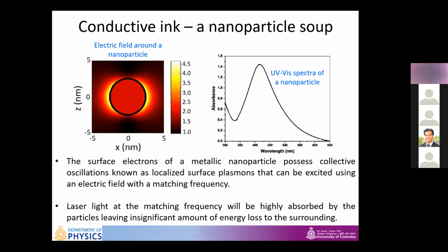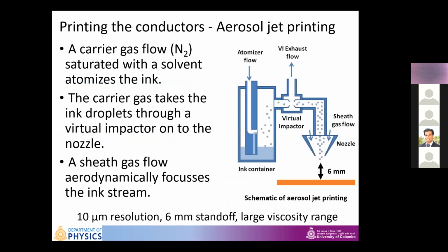So with nanoparticle inks, we have two plus signs. One is that inherently the nanoparticles have lower melting temperatures, and also we can use a laser to selectively heat it and effectively provide the energy for heating without damaging the substrate. So now we have the conductive ink in hand. So how do we deposit this onto the substrate?